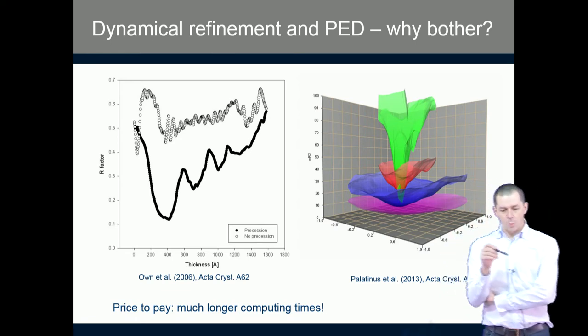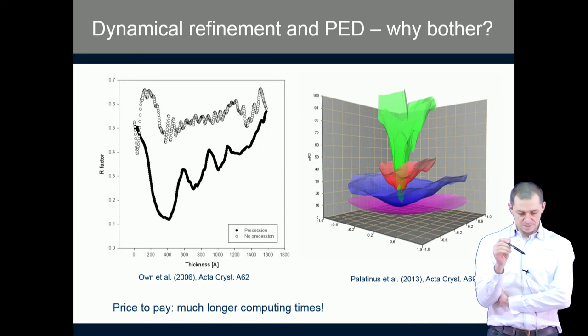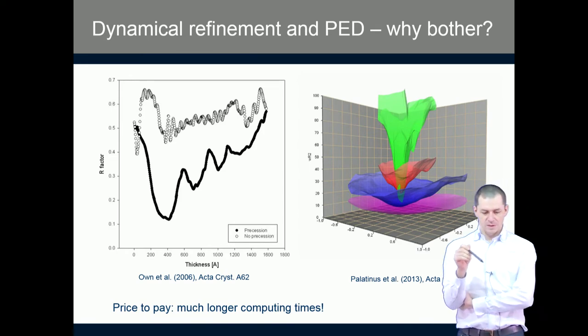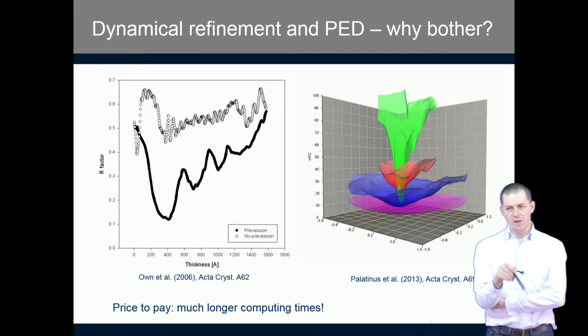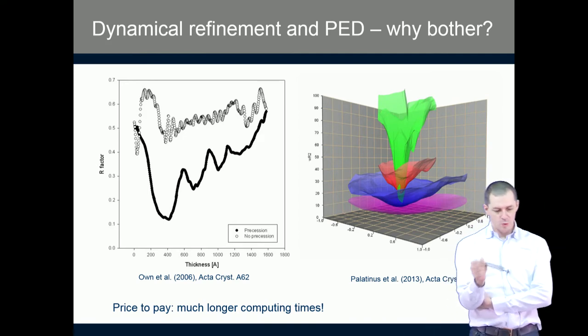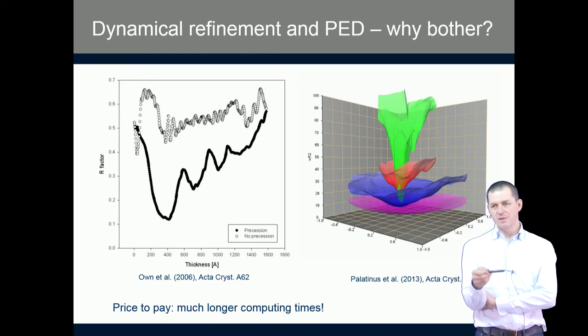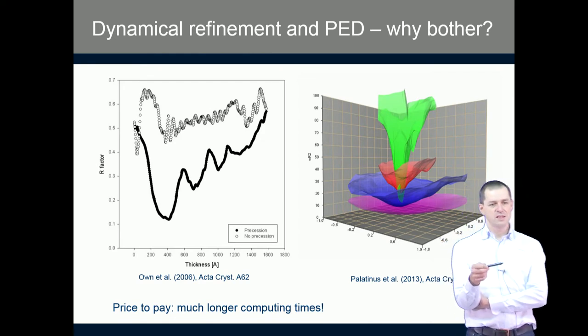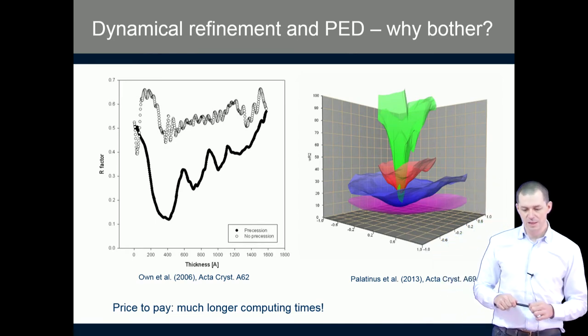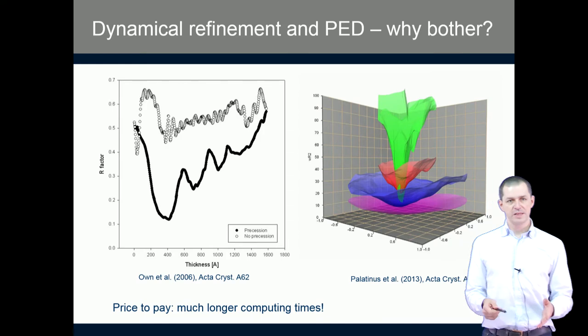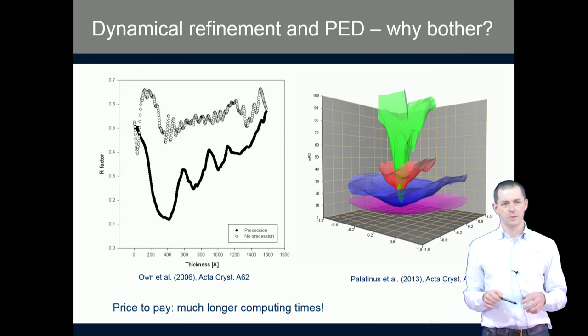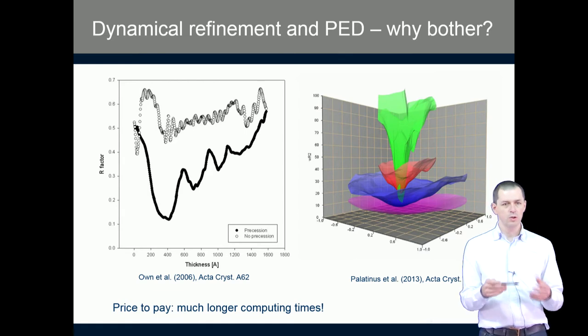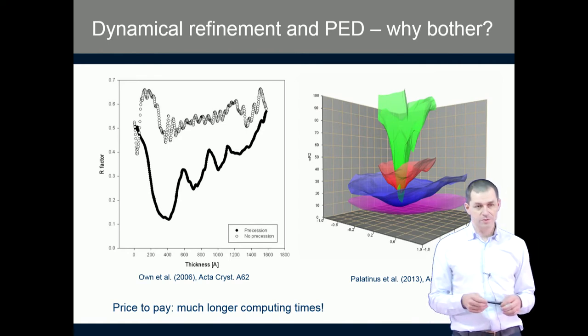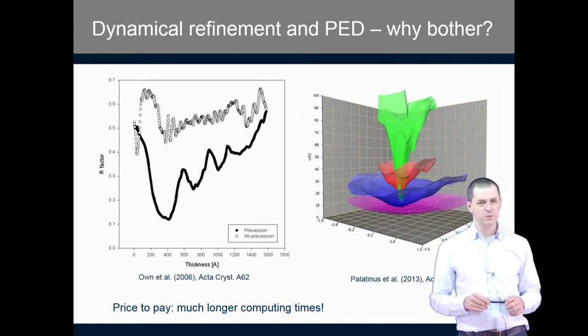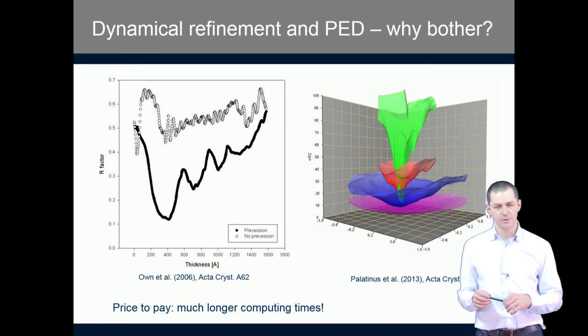You may ask, why do we need to use precession electron diffraction even if we do dynamical refinement? I said that the precession electron diffraction is needed to suppress dynamical diffraction effects, but now I am saying that we have a procedure that includes dynamical diffraction effects in the calculation, so we should not need precession electron diffraction anymore. This is not a good conclusion. In fact, we do need precession electron diffraction for dynamical refinement as well.